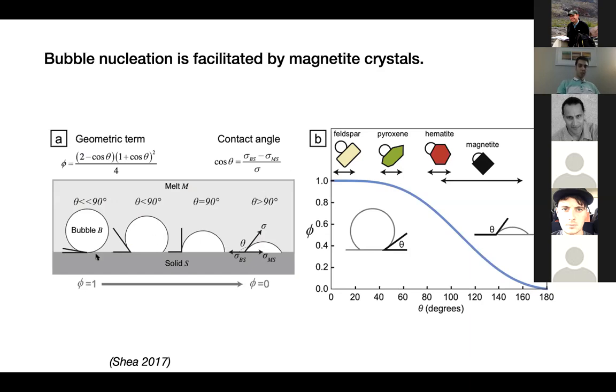Here it's showing that how much nucleation is facilitated by these crystals depends on the contact angle between these crystals and bubbles. The higher the contact angle, the higher nucleation is facilitated. Here it's showing that the contact angle depends on the mineral phase. Magnetite in particular is the most efficient mineral phase in facilitating bubble nucleation.